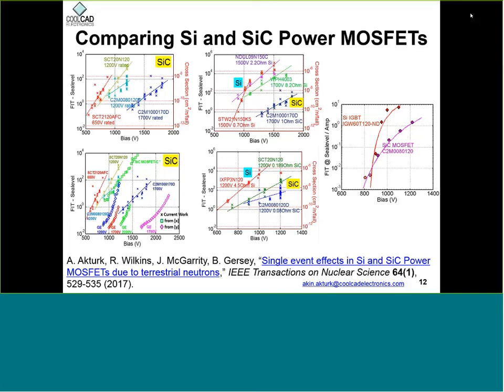So for 1200 volt parts, you generally run the experiments down to maybe 800, maybe even lower. But the experiment time is inversely proportional to the failure rate, so at some point you just cannot run the experiment. For a 1200 volt part, you just don't try to do the experiment at 600 volts, because it takes an extremely long time and you may not get any points. So if they are used at 600 volts and tested at 1000, it may not look too fair, but you can use that information to design a circuit for a 600-volt application.